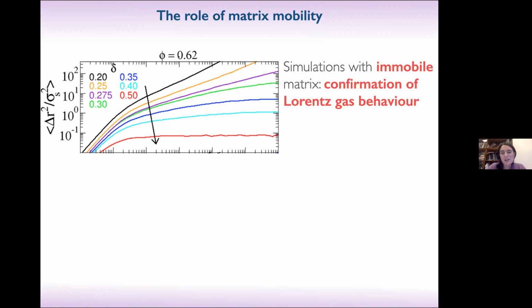That is fixed at this 0.62, we change delta, and you see that as delta increases, the particles become more and more localized. And actually you see the occurrence of the subdiffusive behavior that is predicted by the Lorentz gas at the critical size ratio roughly 0.275.